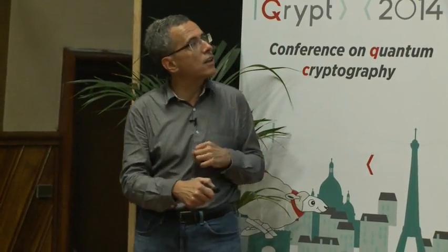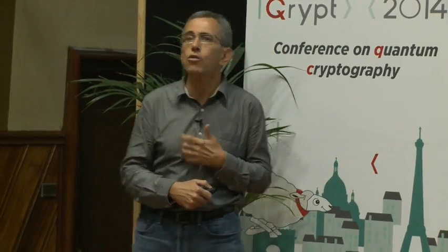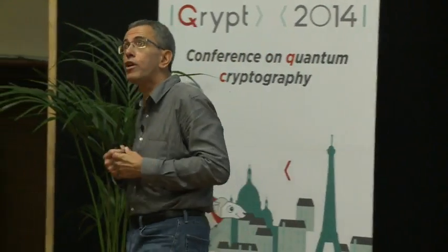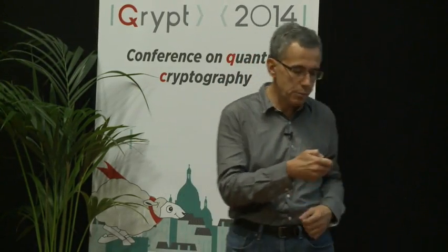Now, the final thing in this category are the shallow defects, or quantum dots. In this case, the optical properties that we are dealing with are really derived from the host semiconductor that is in the background. Probably the main advantage of the system is that it is the one for which nanofabrication techniques have been the most developed. At the same time, it's also the system where the decoherence times are the shortest. So there's always a trade-off in this regard. As I already said, I will focus on quantum dots in the experiments that I'm going to tell you.